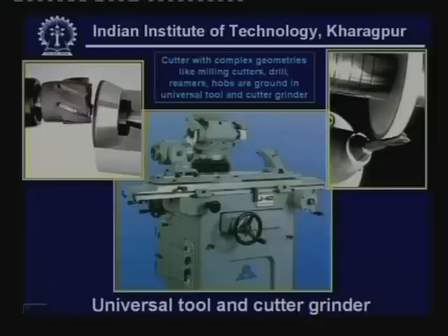But with advent of diamond in various grades, the things have been improved further. Nowadays, this grinding can be performed by this diamond wheel, and these are all resin bonded diamond wheels having a good friability. Particularly, this is essential for grinding the cemented carbide, where this wheel should be free cutting in nature, so that even under dry condition, accurate grinding, precision grinding without any defect in grinding or crack formation on the cemented carbide, that can be achieved by this diamond wheel.